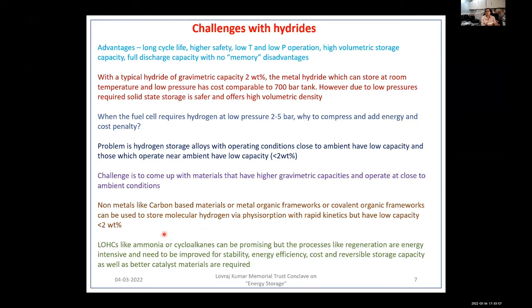They operate at conditions which are close to room temperature and pressure. They have higher volumetric density, and there are materials which can be completely discharged. So whatever you have put in, that amount of hydrogen you can take back. Now, a typical material when it comes to metal hydrides, most of the traditional materials store about 2 weight %. So we can do that calculation that metal hydrides operating at room temperature and ambient pressure can be cost competitive to a 700 bar pressure tank.